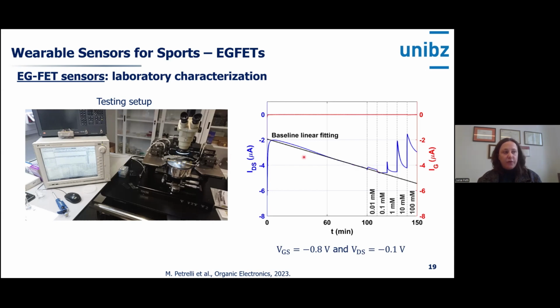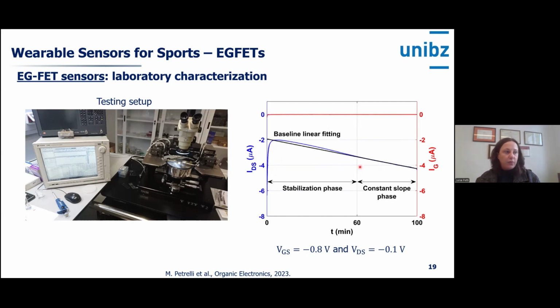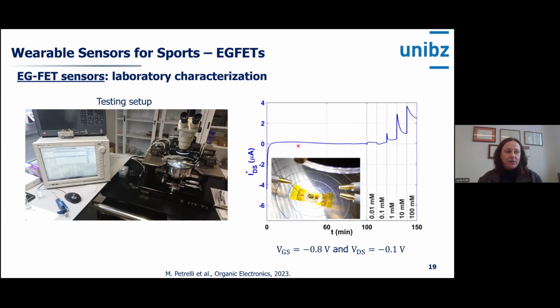We have to do a baseline fitting of the devices because the carbon nanotubes have some variation, especially during the establishment of the two electric double layers. But what you see is that once we account for roughly an hour of stabilization phase, we can then remove that baseline. And then what you see here is the variation of the current upon the variation of the concentration of the ammonium ion, which is pipetted inside the electrolyte.